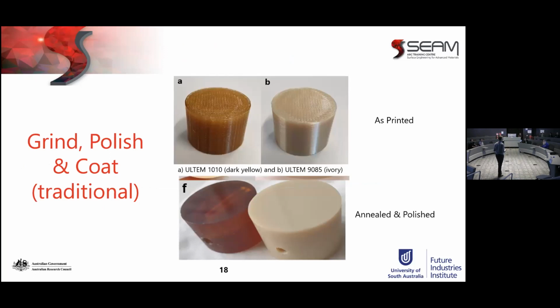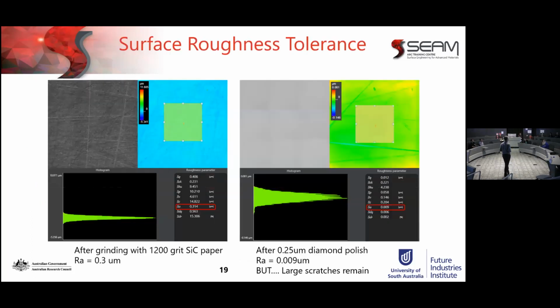Getting onto the plastic stuff. So this is space-grade plastic, two different grades of it. As printed, it's filament type printing, so you end up with a very porous, open structure. If you try and grind and polish that, you'll end up just exposing more and more holes of the porosity. So Jevon worked up an annealing or fusing process and it's a solid object. The approach that we've taken just now is grind and polish. Next on our list is to try the single point diamond turning alternative, and that's happening.